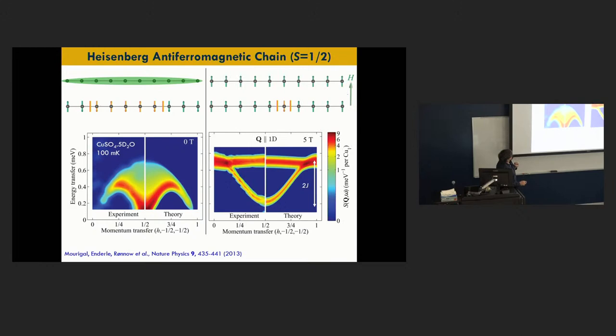But to be sure that this is the case, we did something that was very useful in this material. We apply a magnetic field. And because the interactions are so weak in the system, with a 5 Tesla magnetic field, you can completely transform the system from an antiferromagnet to a ferromagnet. And I told you, in a ferromagnet, I don't have entanglement, I don't have fractional excitation, I just have spin waves. And indeed, you see how the spectrum is completely transformed when I apply the magnetic field. And now you see that for one value of wave vector, I have one energy. This is exactly a spin wave, or a band. It's the band structure of the magnet, if you wish. So this experiment proved that you can tune from a quantum entangled ground state to a product state, a classical state, by using the magnetic field.